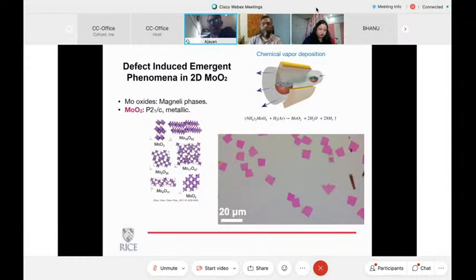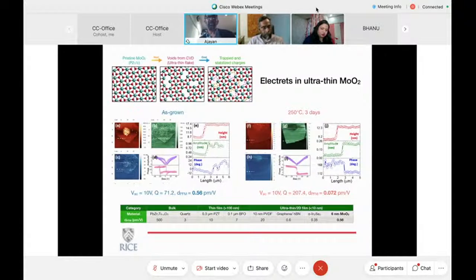I'll just show you one example of other materials that also form in these structures. Molybdenum oxide, particularly the non-stoichiometric oxide of molybdenum, molybdenum dioxide, seems to form these very nice flat sheets during the CVD process. And these are also interesting because you can control the amount of defects in these molybdenum oxides, and you start seeing certain emerging properties like piezoelectricity. In fact, there is a particular name that you categorize these, these defect-induced phenomena like piezoelectricity, in nanostructures and oxides, and also in 2D molybdenum oxides.